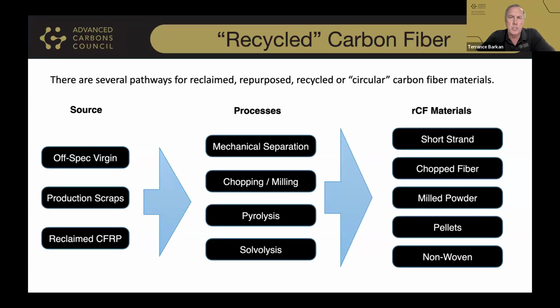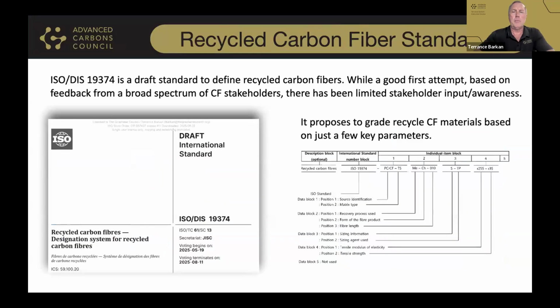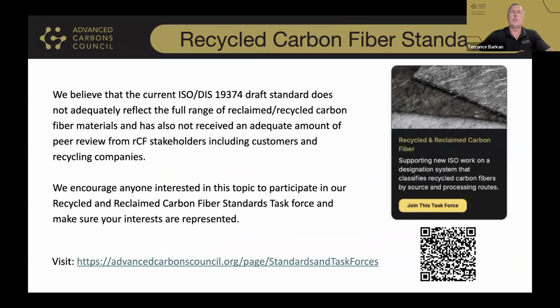What we have seen is that there is tremendous interest and latent demand for reclaimed carbon fiber materials, but one of the biggest obstacles is the lack of consistency or standards for grading systems for the reclaimed or repurposed carbon fiber. There is at this time an ISO draft standard. The ISO DIS 19374 is a draft standard that is within the ISO system, and it does have a proposed system for assigning numbers and grades and categories to some of these reclaimed fibers. However, when we look at it, that standard, which was developed by, we understand, a consortium of 3 virgin manufacturers, has not adequately taken into account the full breadth and depth of the reclaimed, recycled carbon fiber sector, nor has there been enough input from stakeholders who are in that business.